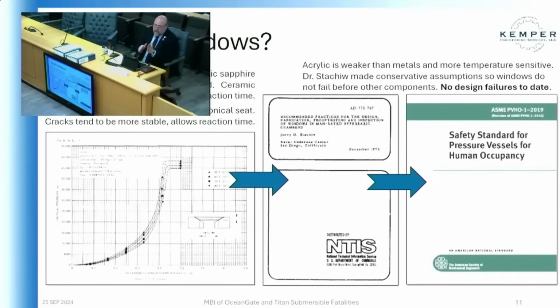The problem with that is that as it sits on a 45-degree angle, 90-degree frustrum, you have this very, very, very stiff ceramic and steel. At some point, as you go down thousands and thousands of PSI building up, water will find a way to jet through. And around 10,000 PSI, a jet is the same jet they use for cutting steel. So if you ever had to do a steam trace where you have to wave the broomstick in front of you walking down a steam trap, and when the stick gets short, you stop, it's the same issue, only worse in a lot of ways.